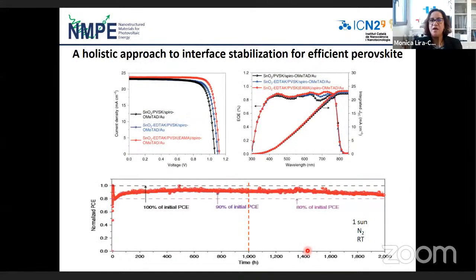Thanks to that, they have been able to obtain very good efficiency of the module devices, and see how very good stability they obtain. They published 2,000 hours under one sun irradiation, also at room temperature, but you can tell it's not an easy task.